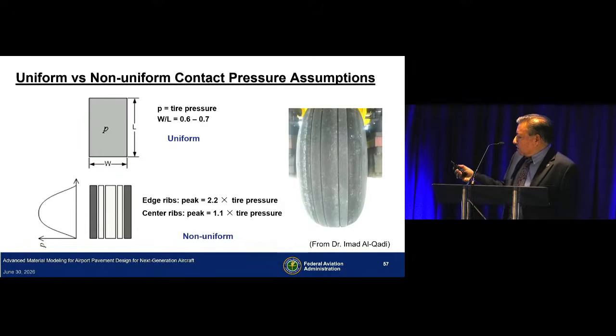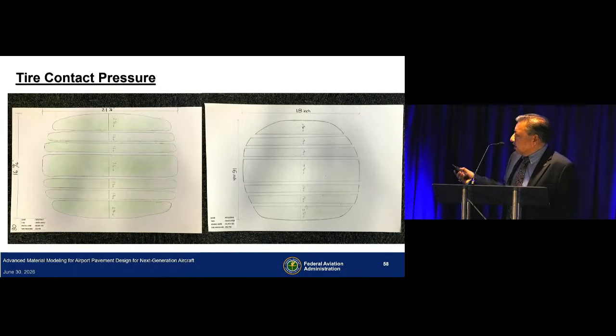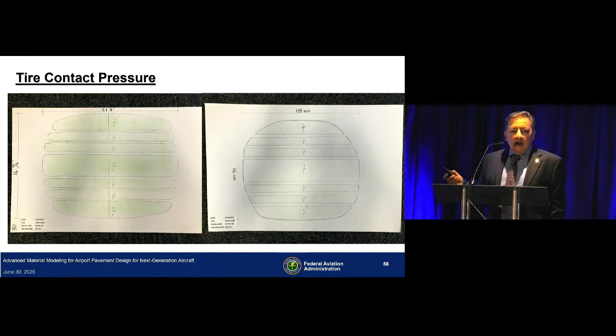And after I saw this work, we have started taking tire imprints under different tire pressures and wheel loads. And just by doing simple math, assuming uniform pressure distribution in all these ribs and taking out the unloaded area, the contact pressure is almost 16 to 20% higher than your tire inflation pressure. So to me, that's an important factor that we should be considering in our design procedure. And the plan is to develop something that can be incorporated into PAVEAIR.